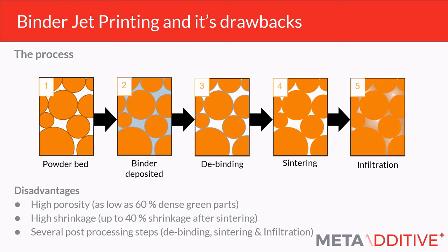and it's not always that accurate. And then sometimes we also need this fifth step, which is a further infiltration process, and we usually use a low melting point metal to do that. So you can hopefully see the steps that are contained in conventional binder jet printing, and the drawbacks are mainly porosity and shrinkage.